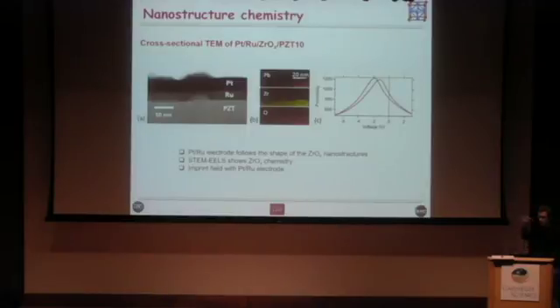Now we grow the electrode, our ruthenium platinum electrode. Here we have cross-sectional TEM, and what we see is that these nanostructures have been preserved. There they are. So the electrode actually follows that topography. You look at some energy loss. It confirms the chemical nature of them, as observed in STEM-EELS. There's zirconium and oxygen. And what we also see in the electrode characterization is there's a strong offset, there's a strong imprint, there's an internal field there after deposition.